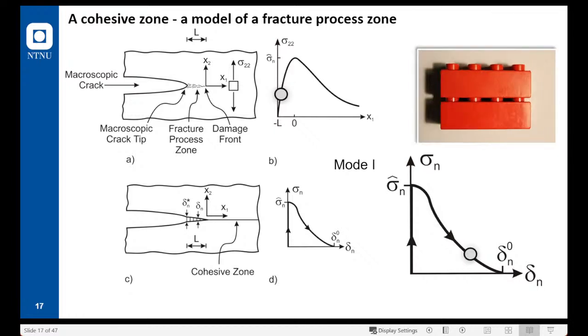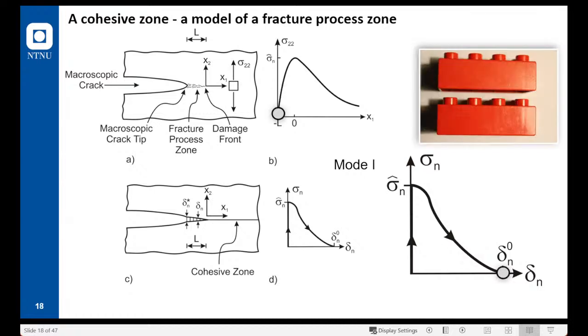If we further increase the applied load, the openings are increasing, the tractions are decreasing, but again, they are not 0. Finally, when the opening is very large, the material is completely broken and the tractions are dropped to 0.